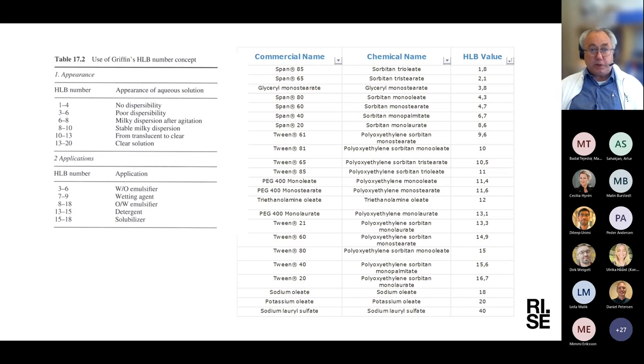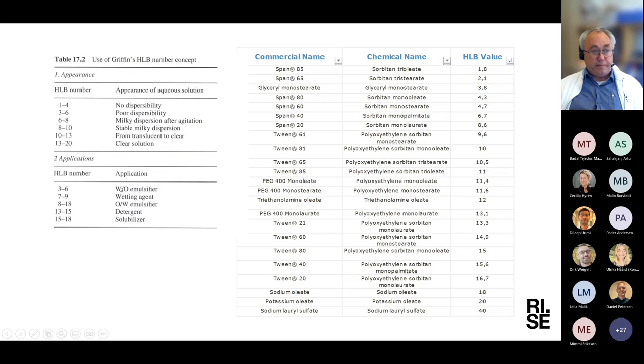Looking at typical definitions and the Griffin HLB number concept: a high HLB number gives a clear solution in water, while a low HLB gives a compound that is not soluble or even dispersible. Low HLB numbers are useful for water-in-oil emulsifiers, intermediate values for oil-in-water emulsifiers, and very high values are more like detergents or solubilizers.